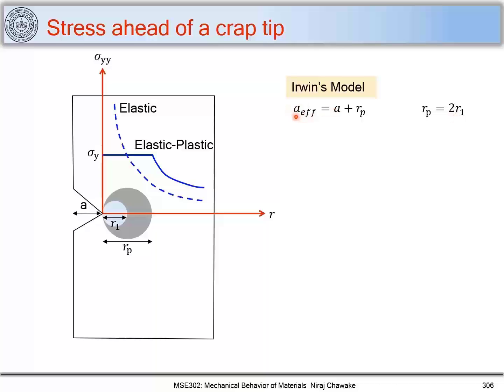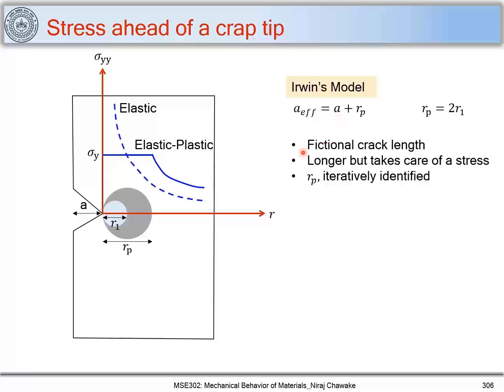And Irwin considers that a effective, that is an effective crack length, is equal to a plus Rp. Now this is nothing but a fictional crack length. If you consider this theory, this model considers a longer crack length, but it takes care of the stress field. So you can see that the stress field will be taken care of. If I consider the crack to be of this length, that is a effective, it can take care of the stress field ahead of this plastic zone. And also importantly, this Rp is found out with many iterations.